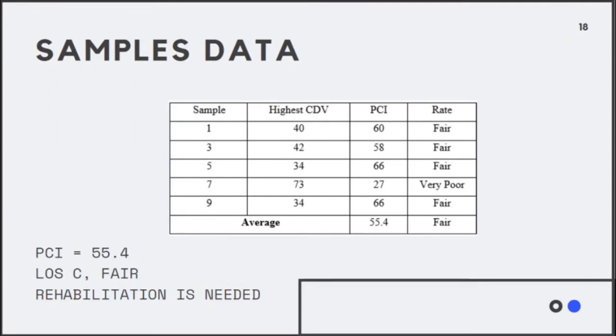The PCI value was calculated by calculating the deduct value, total deduct value, and corrected deduct value. The type and severity of distresses are recorded in the survey form. As the survey form shows, the density and deduct value were calculated and recorded also. We got an average PCI of 55.4, which is considered fair condition and requires rehabilitation.